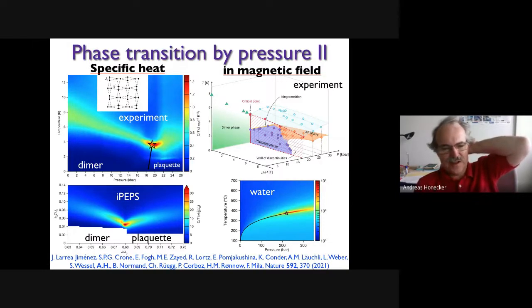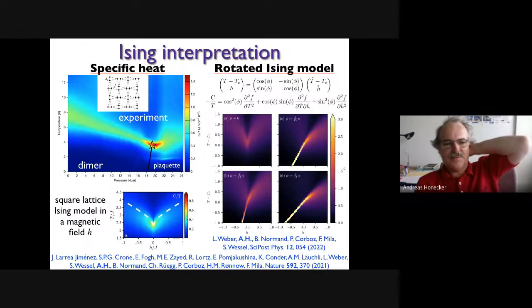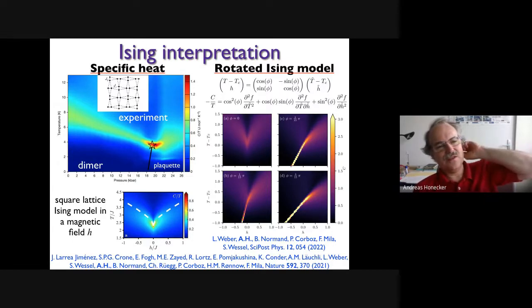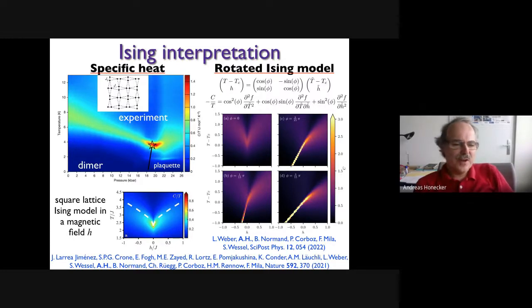So the structure of the phase diagram is exactly the same as you have with water. Well, you might argue that it doesn't look exactly the same. And so that is probably the last point I want to make. So going back to the left, you can argue that what is happening in here, and also in water, is in fact Ising physics. So this is a 2D quantum model, a 2D quantum system that we have studied at finite temperature. You can compare this to the classical square lattice Ising model in the magnetic field. And if you compute the specific heat of that, then you see more or less the same structures as you see here in strontium copper borate, except that the energy scale is quite different.